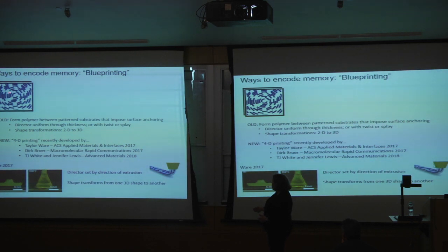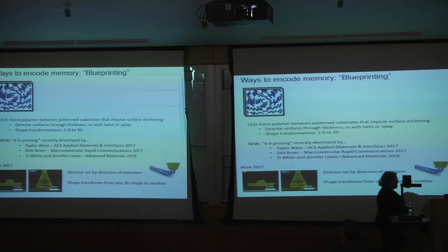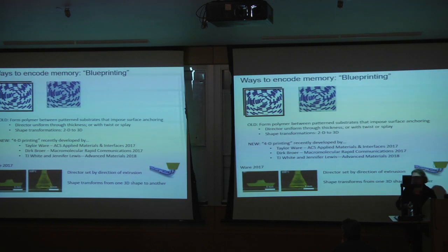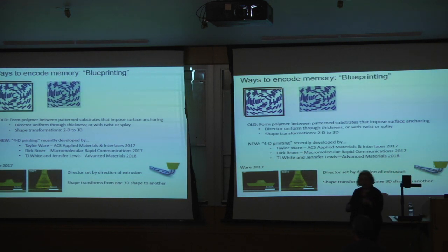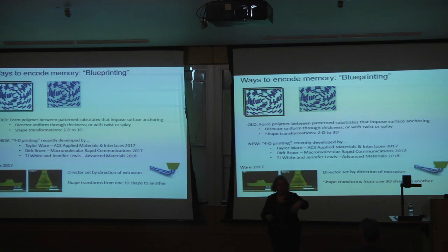So if we have 2 surfaces that have that target pattern inscribed for anchoring the liquid crystal at the surface, then we can put in the monomer, the liquid crystal, the cross-linking agent, shine the UV light through the glass, and then remove the material from the glass, and we get that pattern there. So that was the old way, the first way that these materials were patterned. The name for that is called blueprinting.